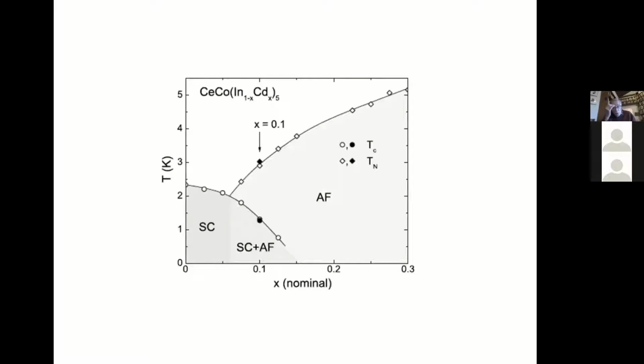So let me go back to the 115s and point out a similar thing happening in these cadmium doped cerium cobalt indium 5 samples. Cadmium doping at low level actually reduces TC, this is just nominal concentration, it's rather small amounts of cadmium that actually go in. And then if you go to more cadmium, it produces antiferromagnetism.